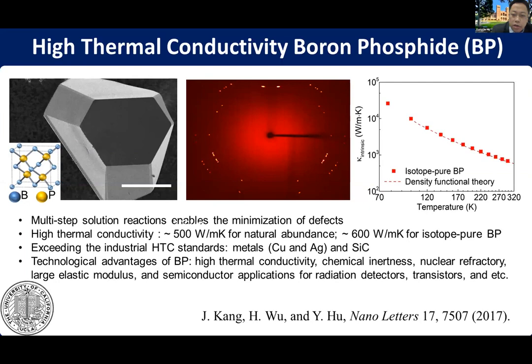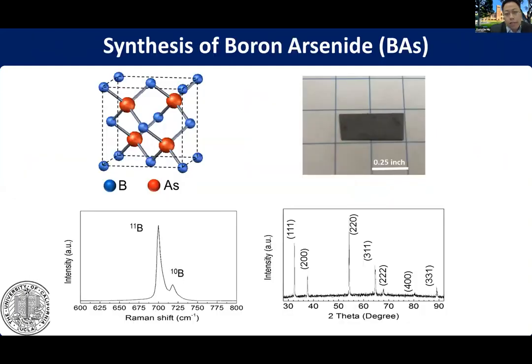In addition to high thermal conductivity, the technology advantages of boron phosphide also include high chemical inertness and nuclear refractory. They also have good mechanical properties such as large elastic modulus. There are other applications such as radiation detectors and electronics. The other candidate is cubic boron arsenide. Boron arsenide is more attractive as initial prediction by David shows very high thermal conductivity, more than 2000 watt per meter Kelvin, even possibly exceeding diamond.